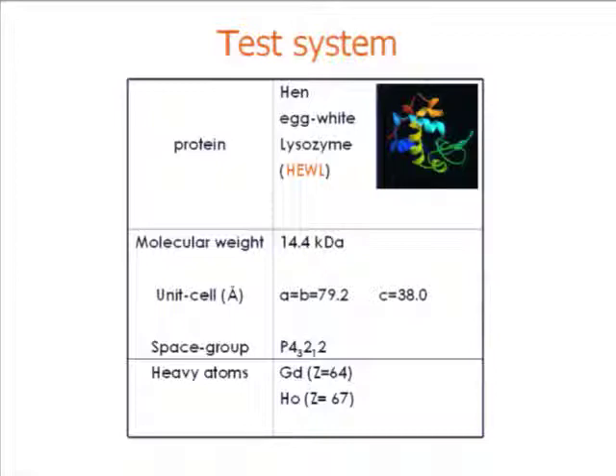Solve the phase problem, and later on solve the structure of the protein. The first time we tried to test whether this method would work well with powder data was lysozyme, tetragonal form, with these lattice parameters and this space group, and it was co-crystallized with gadolinium and holmium, two lanthanides that really have a very strong scattering power.